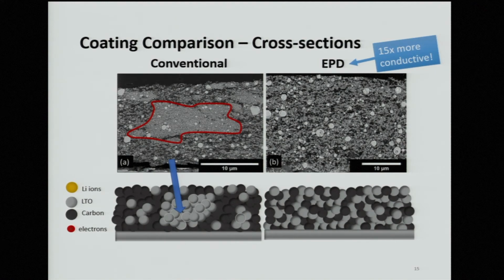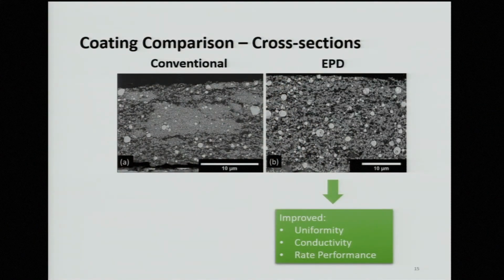Effectively, this is like having a landlocked house that has no access to road. The lithium ions and the electrons can still reach it, but it's a lot slower when it has to flow through the lithium titanate. So we don't have this problem with EPD because we have well-dispersed carbon roads and no landlocked lithium titanate. So now we can say three things. EPD produces uniform electrodes. This improves the conductivity of the overall electrode, and this ends with a better performance as a battery.